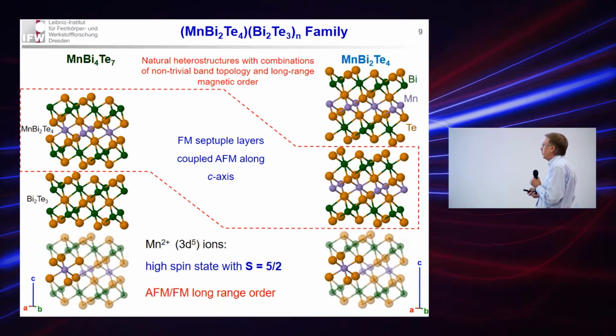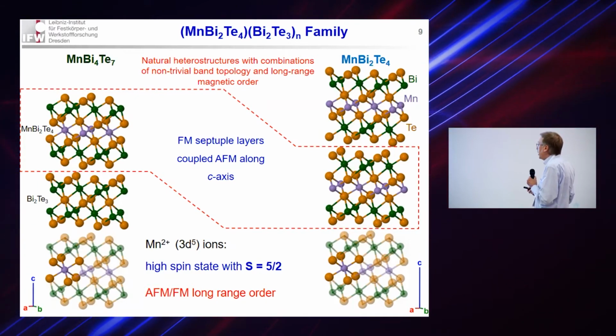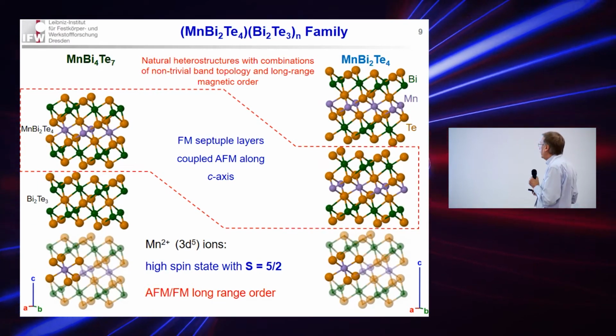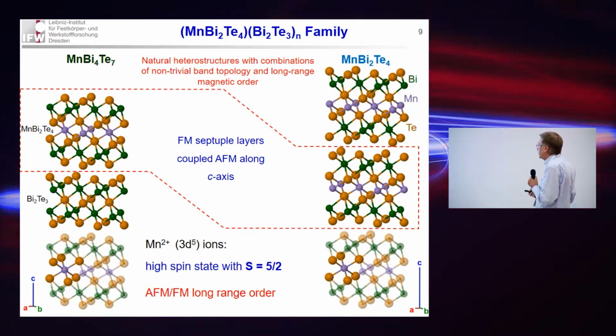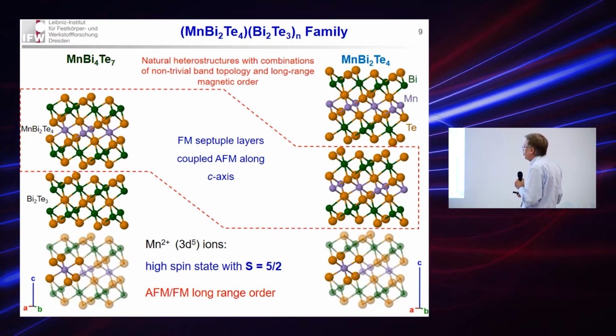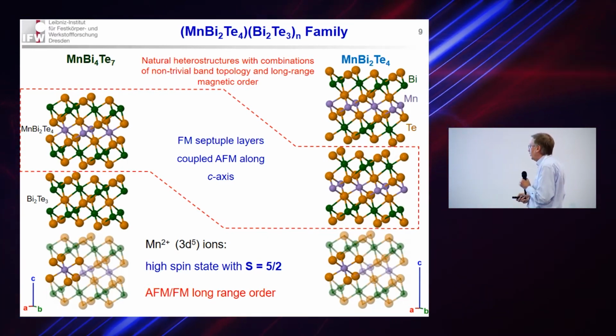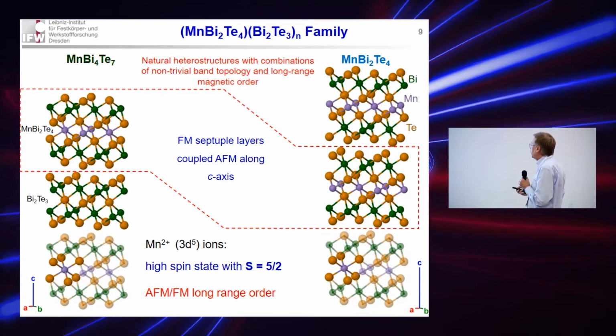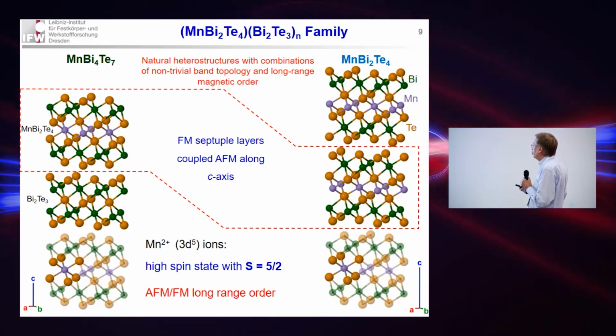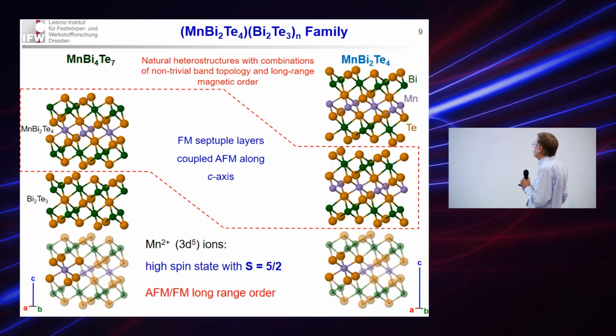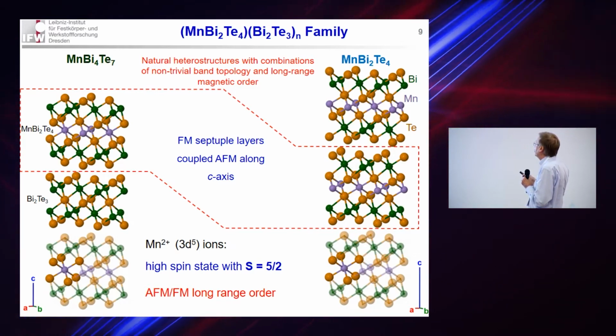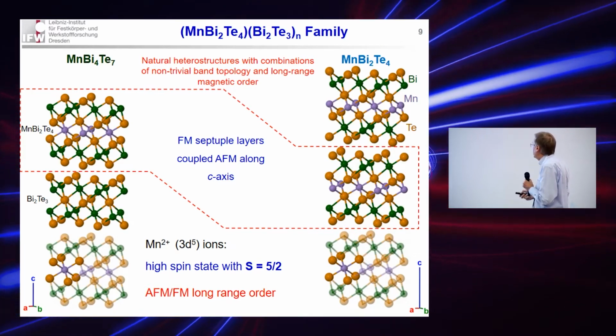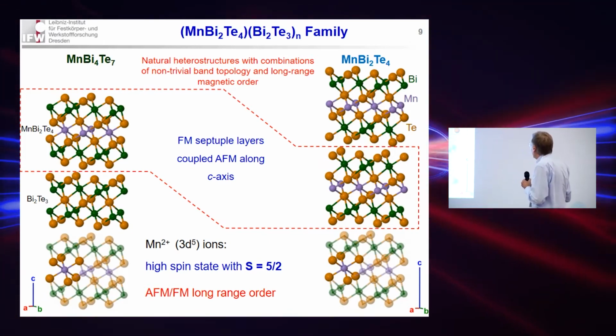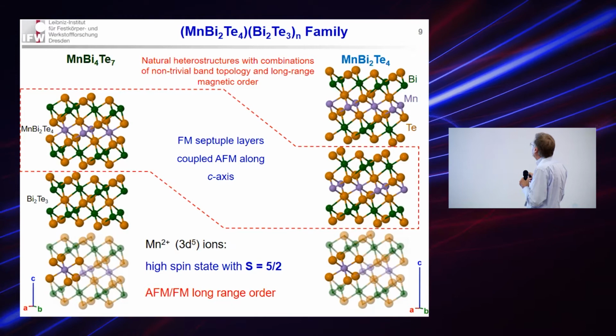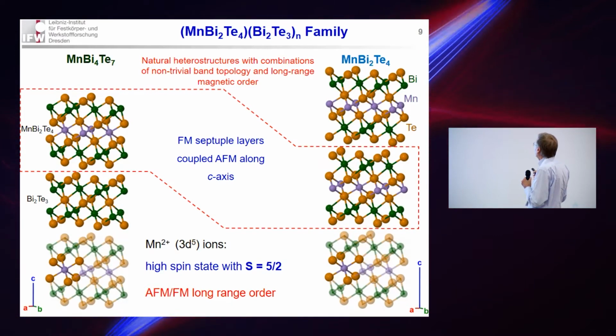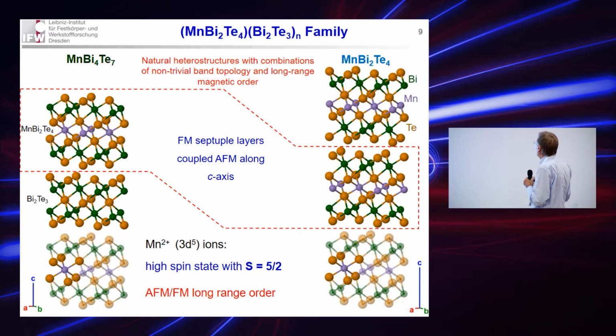an additional double layer inside of it, a manganese telluride layer. So manganese in the 2+ oxidation state has a half-full d shell, a very large spin moment of 5/2. And indeed, the material which shows this structure is the family of manganese bismuth telluride, MnBi2Te4 and family. Actually, the first representative of this family, manganese bismuth 2 tellurium 4, for short 1-2-4, is made